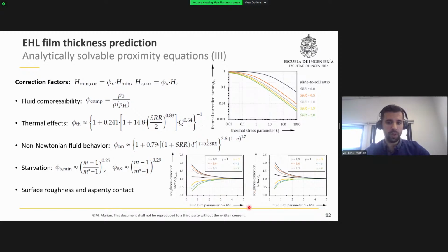And similar to the very well-known flow factor method from Patir and Cheng, they derived corresponding correction factors to adjust the minimum and the central film thickness depending on the orientation of the surface topography and also the ratio of the smooth lubricant gap to the quadratic mean surface roughness, what we know as the film parameter. And to quantify the spatial orientation of the surface topography, they employed a so-called Peklenik factor, which basically is a ratio of the characteristic correlation lengths of two mutually orthogonal measurement directions. So basically, this is a bunch of correction factors that can further adjust the predictions from the film thickness equations.